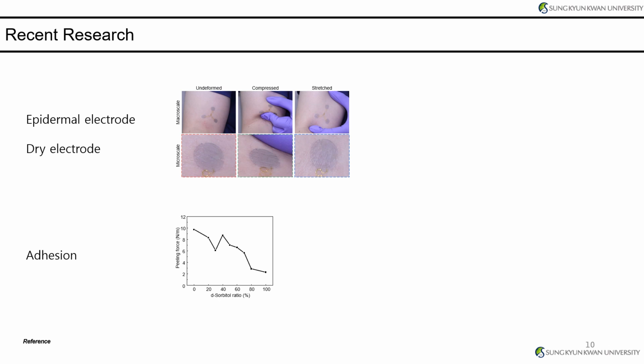In addition, the water-soluble molecules form a linear structure through hydrogen bonding with the non-crystalline PEDOT:PSS, shortening the electron hopping distance and increasing conductivity. The electrode I created is an ultra-thin epidermal electrode with a thickness of 10 microns, made using PEDOT:PSS. Its tattoo-like appearance is very thin, so users feel no discomfort and it minimizes motion artifacts. Moreover, it has good adhesion to the skin even under harsh conditions, which depends on the proportion of the additive.